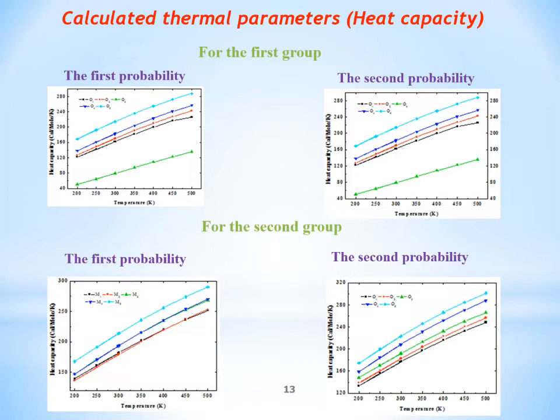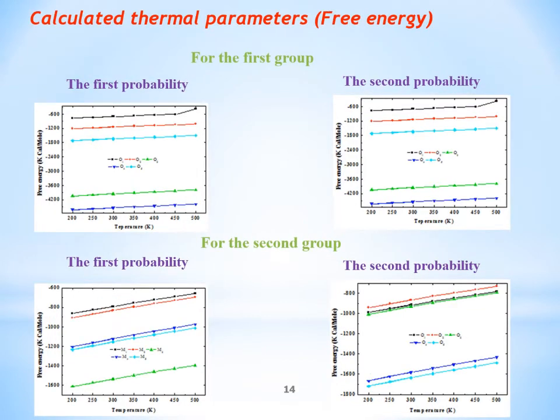By calculating the heat capacity of the two groups at the first and second probability, we find that the low value of heat capacity was also at the first probability in the first group with addition of 2 units of zinc oxide, and the interaction may occur through the zinc atom. Free energy is the energy available in the system to do useful work. By calculation, we see that the free energy has a large value in the first probability from the second group, but also for the first probability from the first group it has a high value.